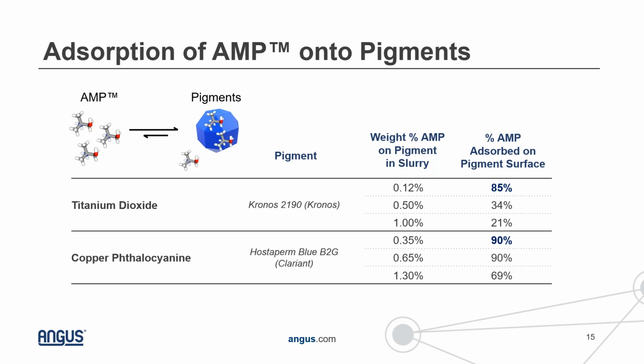And this is a very typical response of a material that has a very strong affinity towards pigment surfaces, which is shown in the cartoon on the top left here. We know from these experiments that if you have AMP in solution and then you introduce a pigment to that solution, much of that AMP is going to end up on that pigment surface. And it's not just for titanium dioxide. In the case of the blue pigment here, which is copper phthalocyanine, a typical blue pigment, we also see very strong adsorption of AMP onto that colored pigment particle surface, even more than for titanium dioxide in this case, so up to 90% adsorption.